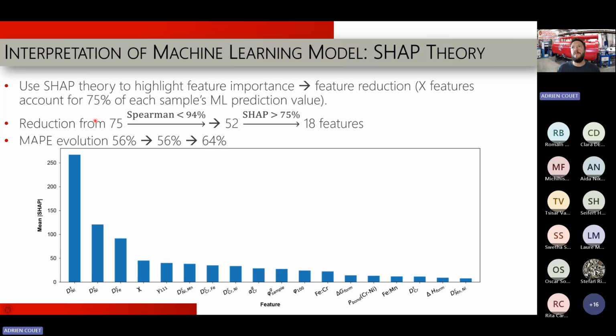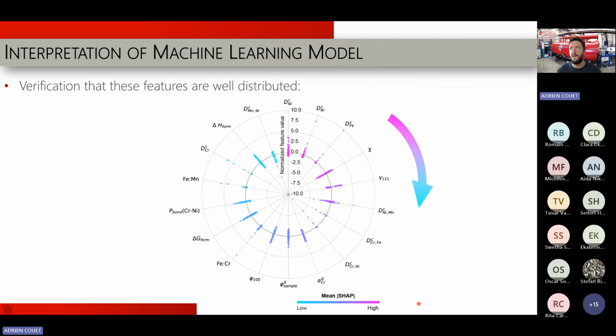So with this, we can go from 75 to 18 features using Spearman pruning, and we only increase our error from 56 to 64%. So we lose very, very little accuracy by reducing the number of features by a lot. And all the features are shown here at the bottom. I won't go into the detail of those right away, but there are about 18 features that we have kept here. So what do we do with those features? There are 2 main plots that we put together, which are plots that you don't see out there a lot, but I think they're actually quite interesting to look at the results.